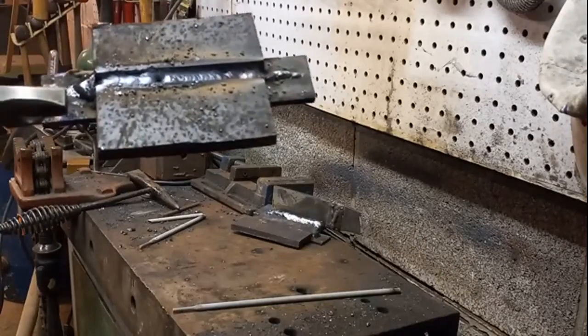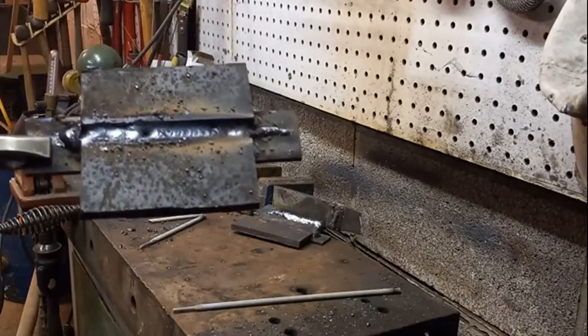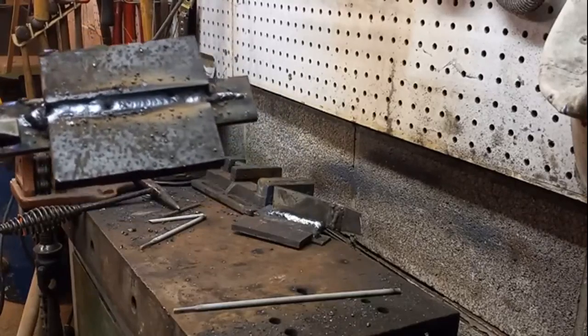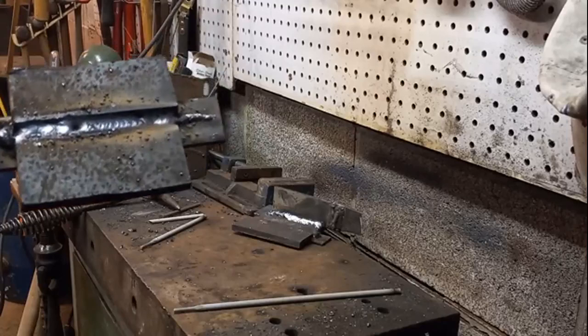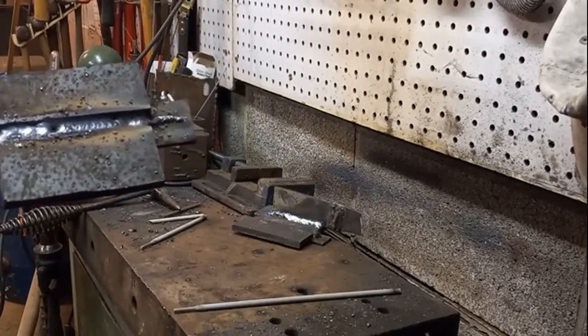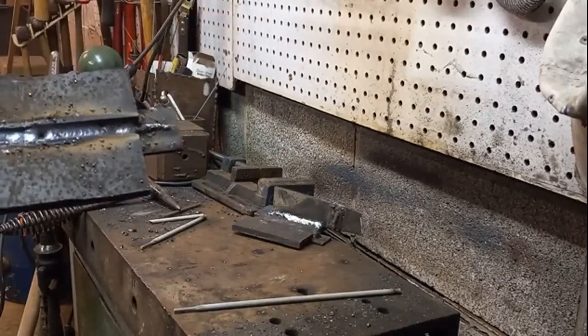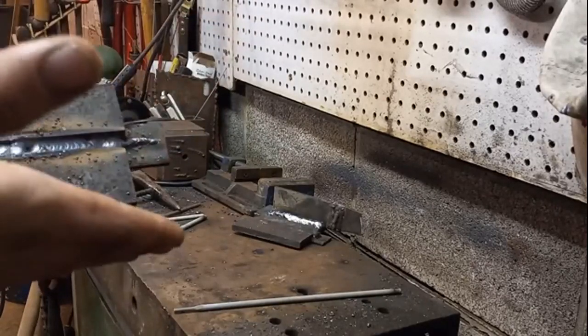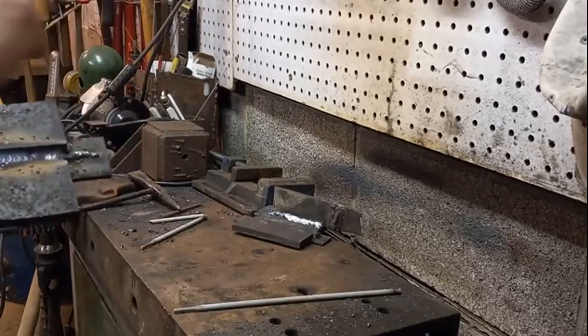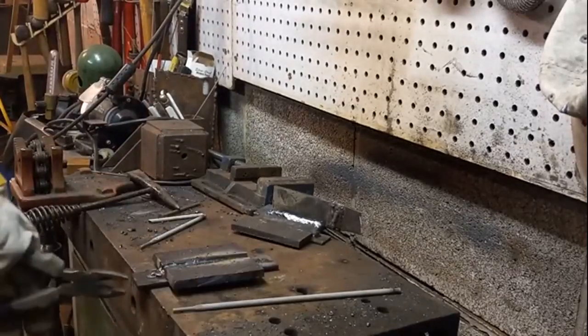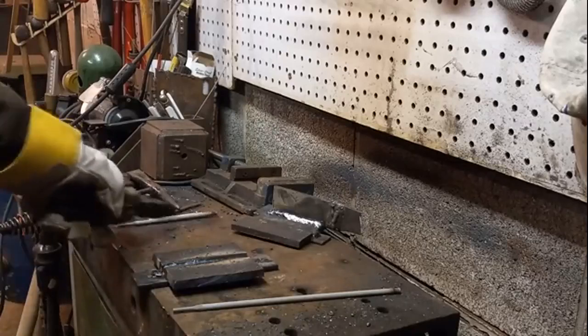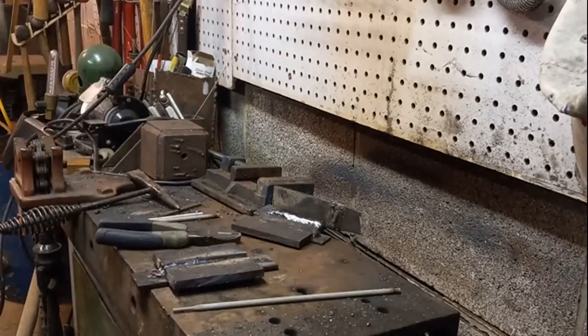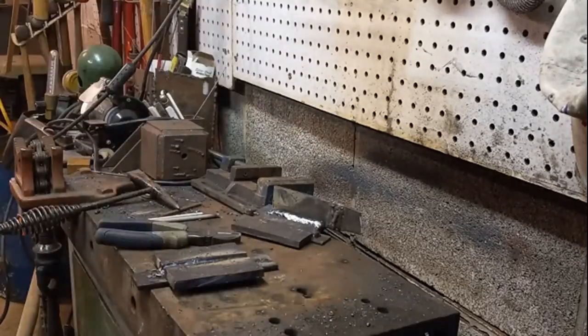Alright, so the second bead over, I started as a slow weave, but whenever I hit that slag inclusion from the previous weld bead, because of the insufficient gap, the arc was sputtering a lot, but it kind of kept going. I went from a slow back and forth weave into a stringer bead, and I still have a slag inclusion in there. Ideally, I would grind this out. You grind it out, and you redo that weld, but I don't really have the time right now, or the motivation, to be honest. I'm just going to do another bead over top of that. It'll make it disappear. It'll still have a slag inclusion with this. This is an X-ray, just a demonstration of it. And that's kind of what you expect from 6013.